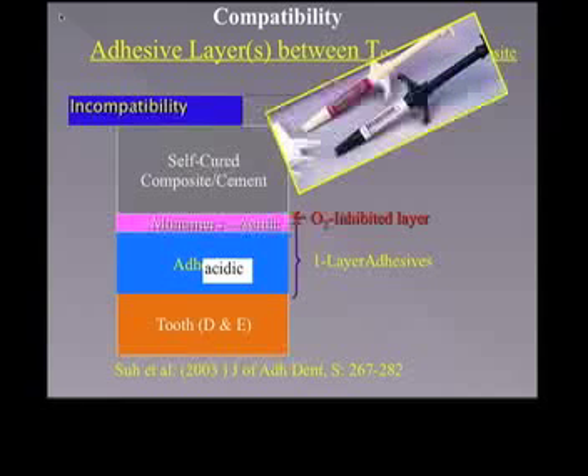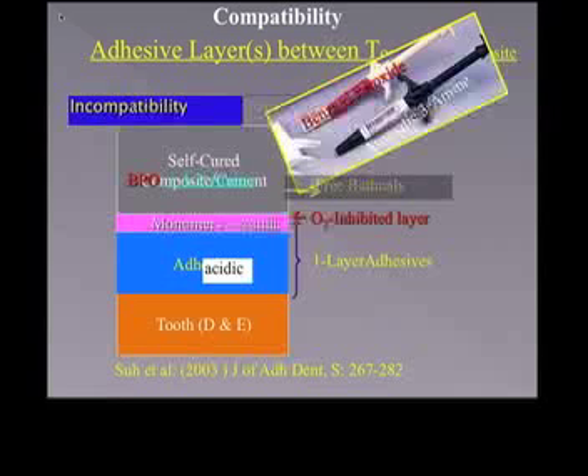Inhibiting the cement's self-cure, or incompatibility, occurs only at this adhesive interface, while the remainder of the self-cure reaction continues. The bulk of the cement feels hard and is perceived as acceptable, when in reality there are significant clinical consequences to pay. In other words, it's not setting up totally because of this reaction with benzoyl peroxide. So be careful.